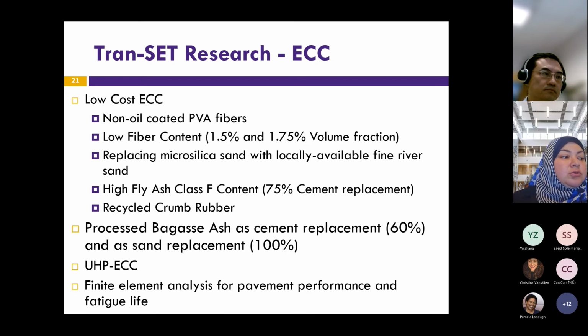And we looked further, so if this is successful, what else can we do? We started experimenting with other types of ash other than fly ash, and we experimented with processed bagasse ash. We used that as a replacement for both cement and sand. Actually, the ECC modified with non-oil coated fiber and bagasse ash is a patent that we just got approved last month. So we can produce any ECC with non-oil coated fiber that has bagasse ash in it.